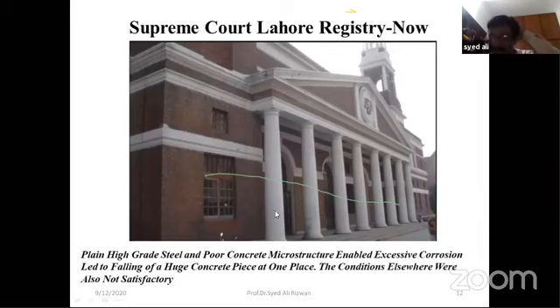So the old buildings also used this cold twisted steel sometimes, but this building never used a cold worked steel, but used a high grade, maybe high carbon steel. But the main reason for that localized failure was corrosion. The conditions elsewhere were also not satisfactory because the crack lines could be seen along the reinforcement lines. So this was the second case which came to our notice.